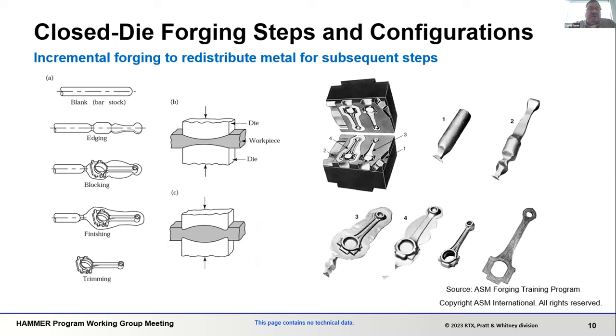The issue of forging has always been a bit of a problem where you're trying to make shapes and the shapes are not uniform in cross-section. And so you can be starting off with bar stock, which is uniform in cross-section. And then you need to start to gather material, thicken it up in cross-section, reduce it in other cross-sectional areas, put it into closed dies and start to make shapes, and then finally finish and trim the parts. The tools that are used to do this sometimes are actually closed dies, such as a blocker or a preforming tool, but they can also be done in an open die configuration, where you can have a fullering die where you're pushing material out, or a die for gathering and bringing material in to a given area. So again, this is an issue of the manufacturing processes that can be used, and they can be automated, right, to do these things. You can program them.